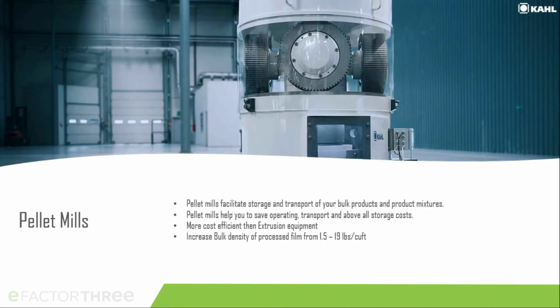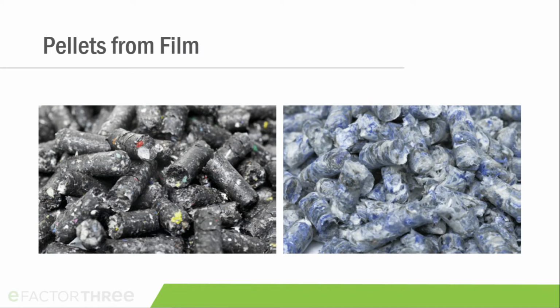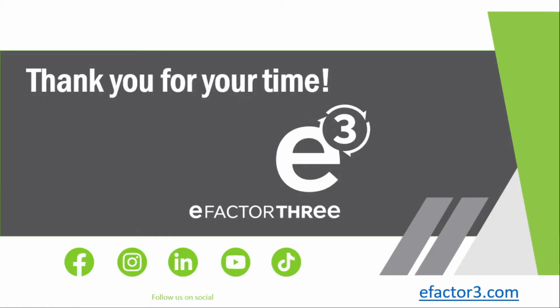And then when it comes to the film, since it becomes fluffed up so badly through the process, a lot of people have to get a higher density out of it. So by utilizing a pellet mill, you can increase it from 1.5 pounds a cubic foot to about 18 to 20 pounds a cubic foot. This is what these pellets look like. They have good flowability, easy to mechanically convey. And yeah, that's about all I have to say today. So if you have any questions.